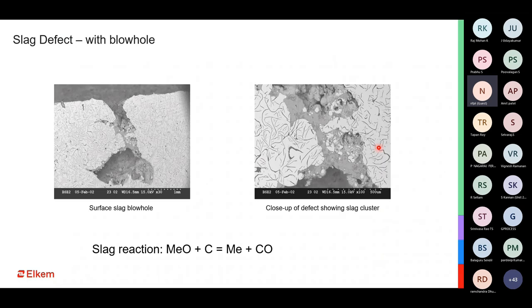So in many cases, the slag inclusion is combined with gas defects in the casting, and thereby it becomes difficult to identify whether the problem is related to slag or just to gas. We have seen a lot of cases where foundries started to look at gas defects and tried to find a solution to them when the actual problem was the slag which was getting entrapped within the casting and was actually the reason for the gas defect.